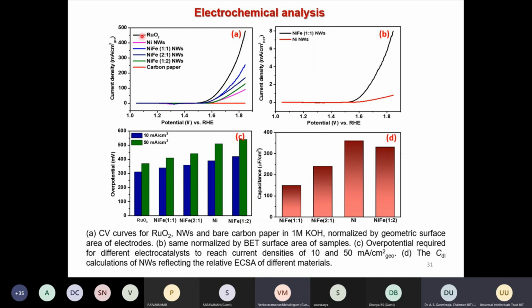And we have compared ruthenium oxide, which as I said is one of the benchmark catalysts for the oxygen evolution reaction. This is for the nickel nanowire, this is nickel, and this is nickel iron. You can see different ratios, we have done 1:1, 2:1, and of course 1:1 is the optimized structure, and only the carbon paper. We can see that this is the ruthenium oxide value, which is again better, but next to this is the nickel iron 1:1 nanowires.